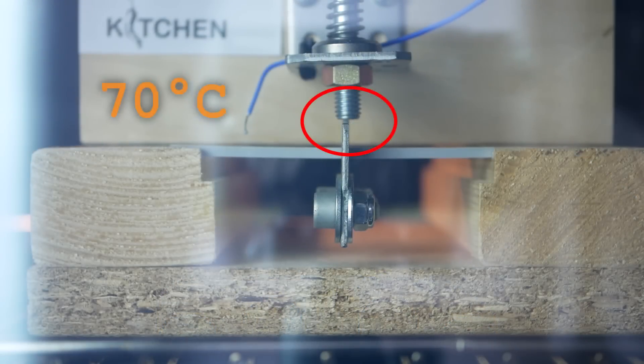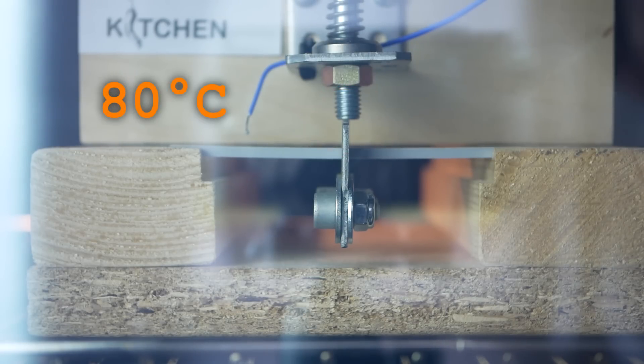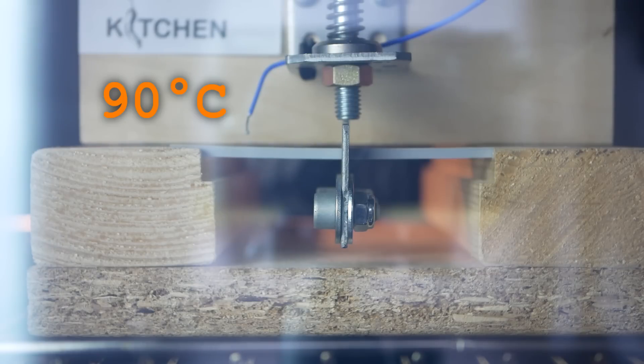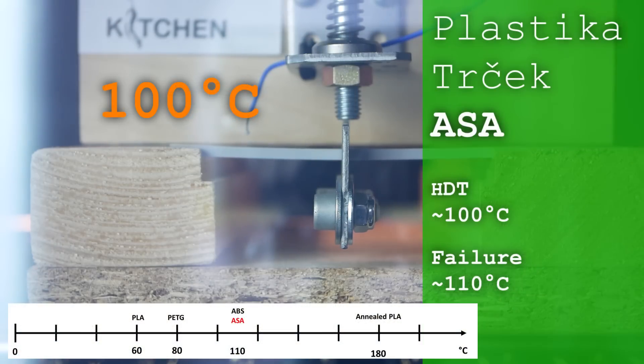The temperature test showed that the material started to soften at around 100°C and totally failed at 110°C which is remarkable and makes it well usable for many temperature demanding applications.